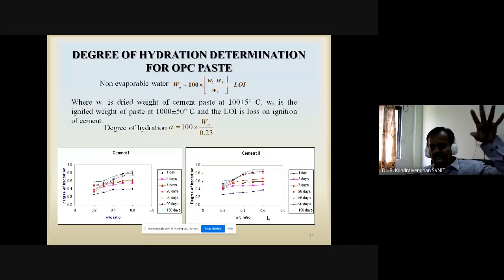So we have determined it experimentally for a number of samples, for different water cement ratios and different curing ages. Once you know the non-evaporable water, we can calculate the degree of hydration. The degree of hydration is nothing but the non-evaporable water divided by 0.23, because 1 gram of cement has 0.23 grams of combined water.